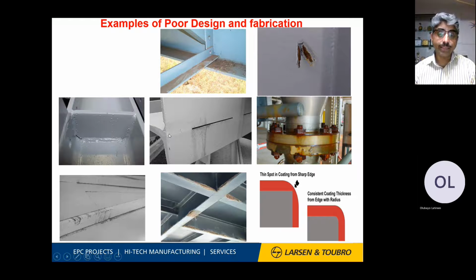Again, poor design. These are flush joints for the weld, and the other side is also the same, and this is what the gap is. Through this gap the corrosive product gets inside and accumulates and forms a localized crevice, and it creates premature failure of the components. Similarly, if you see the flange joints, because of leakages due to poor tightening or a mismatch between the gasket face and the flange face, it leaks out, and because of that you find heavy rusting over the bolt joints.